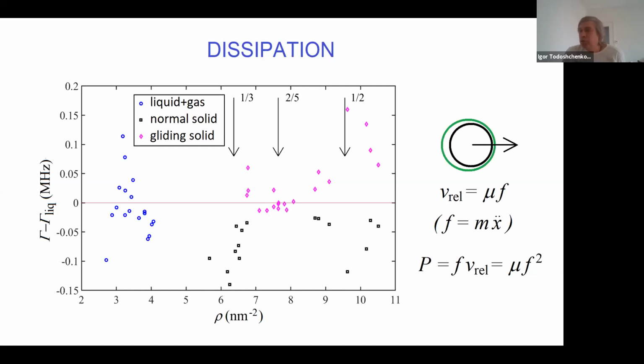Helium creates additional dissipation to the tube. Why is that? Because when the nanotube is moving, this is a cross section, the helium is always lagging behind the nanotube, and there is always relative motion between the nanotube surface, nanotube atoms and helium atoms. And this can be expressed as a mobility mu times inertial force, which is just the mass of helium and acceleration. And if we now calculate the dissipation, power is proportional to the force times V, which is F squared and mobility. So the larger the mobility of the phase, the stronger the dissipation.